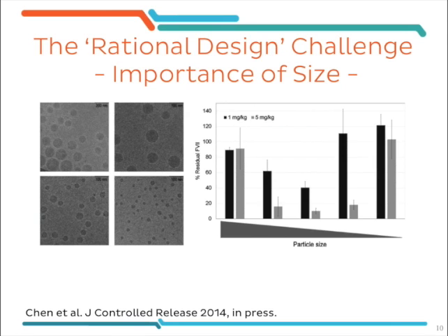versus, so sorry, this is what we have on the y-axis, so versus the particle size of the respective particle formulations. And as you can see, it's not the very large, very small particles, but rather the particles of a specific intermediate size that are the most potent in knocking down this gene. So a specific nanoparticle size is needed to get the best in vivo effect.